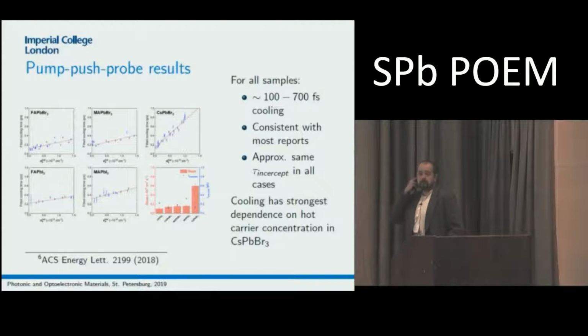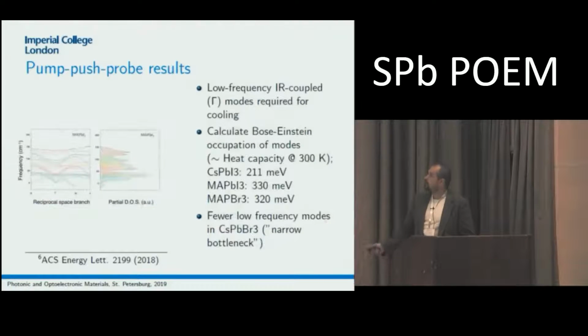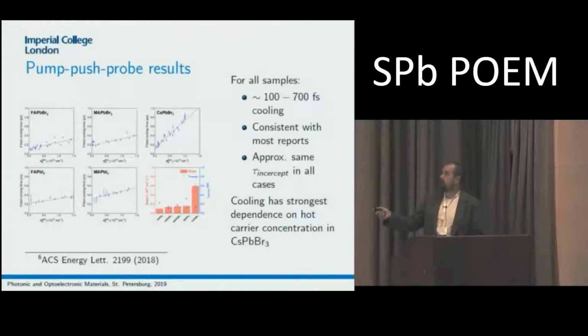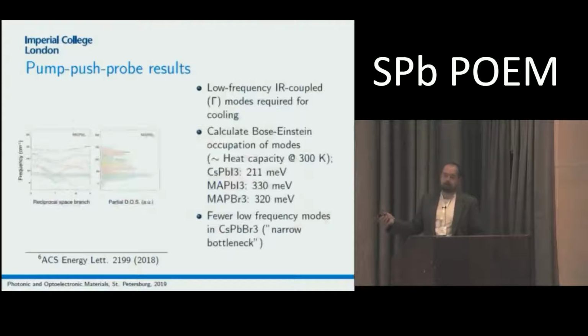These data would be consistent with most reports, but this was the first direct measurement of hot carrier cooling, so we published this last year. Then we have some theoretical analysis performed by the theoretical group in the materials department. The higher slope in this material would be associated with a so-called more narrow bottleneck, which describes the interaction between phonons within the lattice and hot carriers.